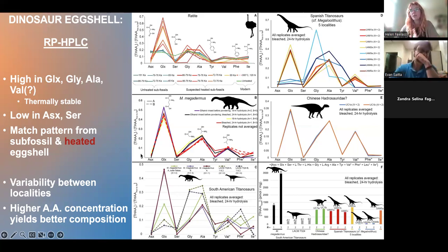And so how confident can you be that those are endogenous and are not part of the contaminants that you can see with the LC aspect? Well, that's always the question when you're dealing with low concentrations. But there are various lines of evidence. One being, if it's contamination, then you have to explain why the profile matches that of a diagenetically altered modern dinosaur eggshell. For example, why is it that you consistently get this strong glutamic acid peak followed by glycine and alanine and then maybe valine, as opposed to the reverse, where glutamic acid is really low and you have really high glycine? So the profile itself is consistent.